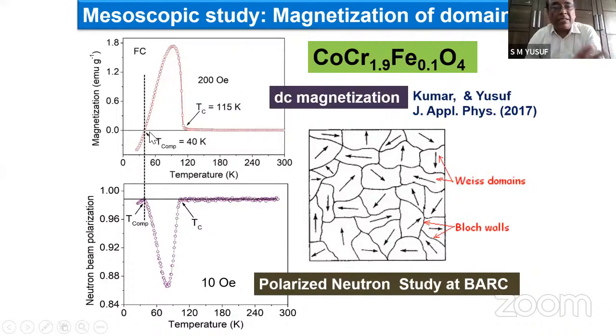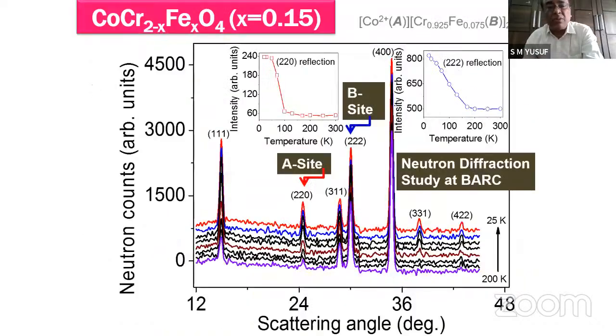This is the direct evidence that domains are having 0 magnetization at this particular temperature, but not above or below. After this, we'll also show the neutron diffraction data, where you will see that even this cancellation of moment is taking place at the unit cell level, the magnetic unit cell level. So as you know, within the domain, for students, how many magnetic unit cells are there? The cancellation taking place at the unit cell level comes from neutron diffraction, and neutron depolarization said the cancellation is coming from the domain level. Obviously, if the unit cell has no moment, the domain has no moment, so the net bulk magnetization measurement is also 0. So this is what I want to bring clarity to.